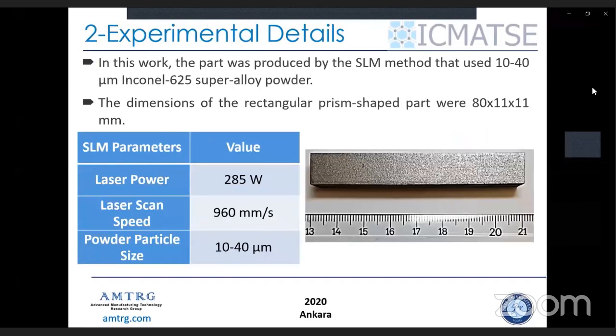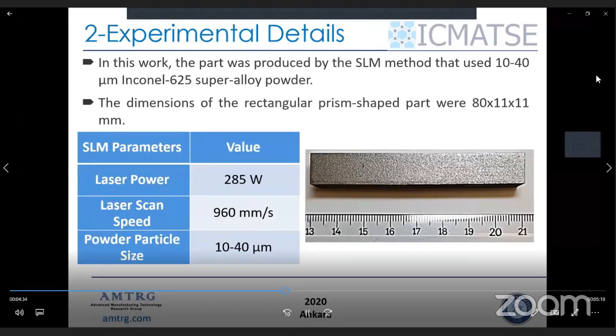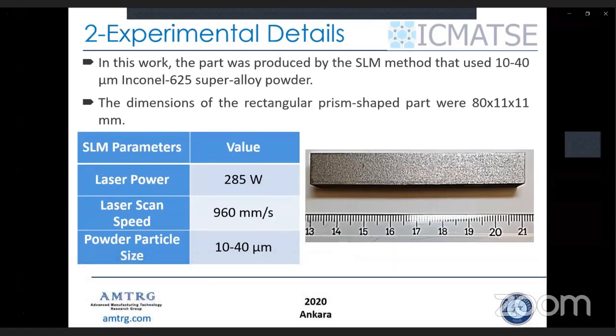In this work, the part was produced by the SLM method that used 10 to 40 micrometer Inconel 625 superalloy powder. The dimensions of the rectangular prism-shaped part were 80, 11, 11 millimeters. The table shows the parameters of SLM. Laser power was selected as 285 watts. Laser scan speed was 960 millimeters per second and the powder particle size 10 to 40 micrometers. And then the actual laser polishing was applied on this surface.